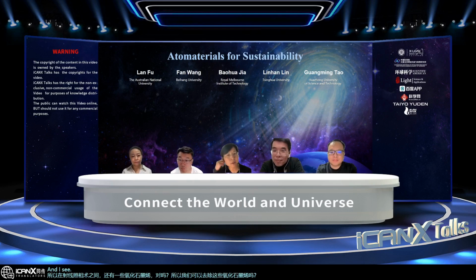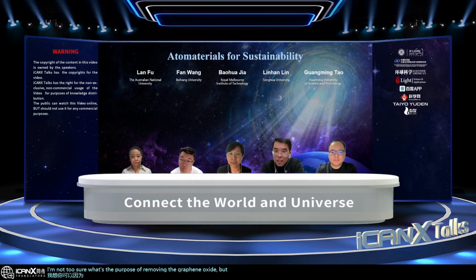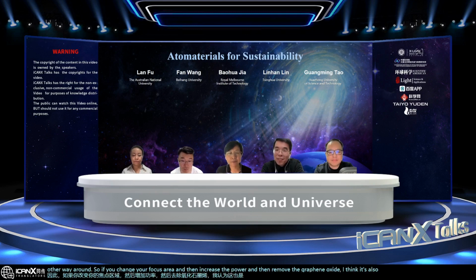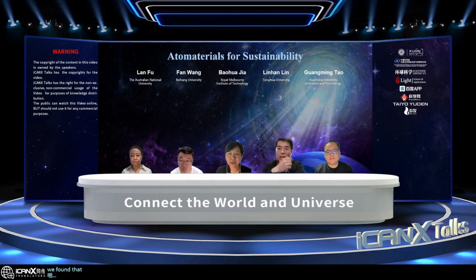I think you can, although I'm not too sure what the purpose of removing the graphene oxide is. But what we did before was, if you increase your laser power continuously, you are able to remove the reduced graphene oxide. But the other way around, if you change your focus area and then increase the power and remove the graphene oxide, I think it's also possible. We found that actually the removal process is also very interesting.